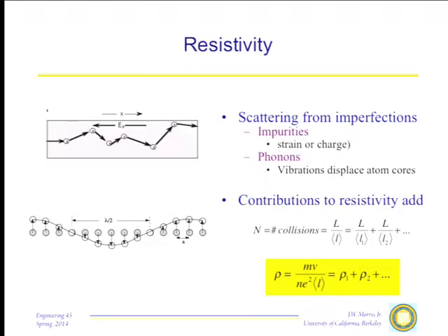Resistivity, well, to go a little bit further, of course, even with good metals, the resistivity or the conductivity can vary quite a bit from one to another. If you go into a hardware store and you start looking for copper wire, you will find for sale several different grades of copper wire at different costs. And those different grades of copper wire basically will differ in the purity of the wire. Usually the best stuff is OFHC, oxygen-free high conductivity. But the microstructure of the metal does have a significant effect on what its conductivity will be.